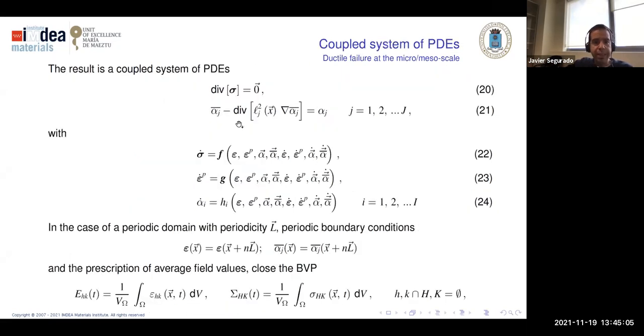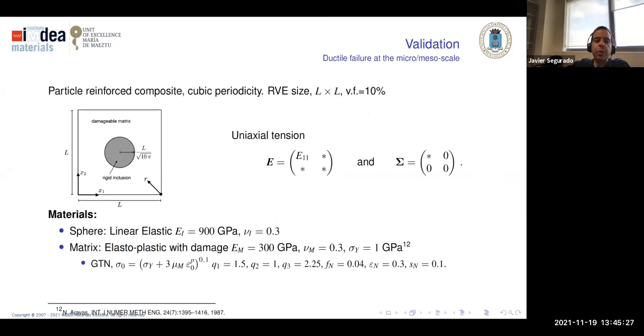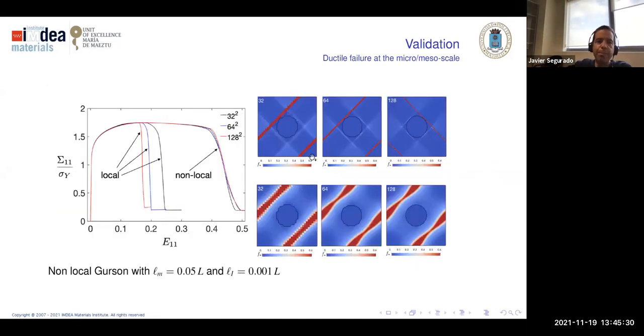Okay, so at the end, from the mathematical viewpoint, we have a coupled system of PDEs. We have the standard equation for sigma, and we have one of these Helmholtz equations for each of the variables that we are making non-local. Okay, and this can be solved in a staggered manner within FFT. Again, I'm not going into the details, but to the results, and let's see what is the effect. So if we go to a very simplistic two-dimensional framework of a particle-reinforced composite, elastic particle within a matrix, what we see with the local model is localization.